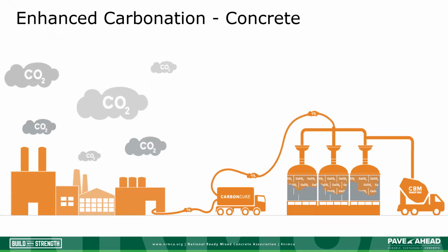Other commercially viable technologies accelerate carbonation of concrete. This is accomplished by either injecting CO2 into the concrete or curing concrete in CO2. One company, CarbonCure, uses CO2 captured from industrial emissions, which is then purified, liquefied, and delivered to partner concrete plants in pressurized tanks. This is then injected into the concrete while the concrete is being mixed, which converts the CO2 into calcium carbonate within the concrete. The process reduces CO2 emissions in two ways: through direct sequestration of CO2 injected into the concrete, and by reducing the cement demand, since this concrete requires less cement to produce concrete at a specified strength. Studies have shown that enhanced carbonation typically enhances concrete's compressive strength while reducing cement content.